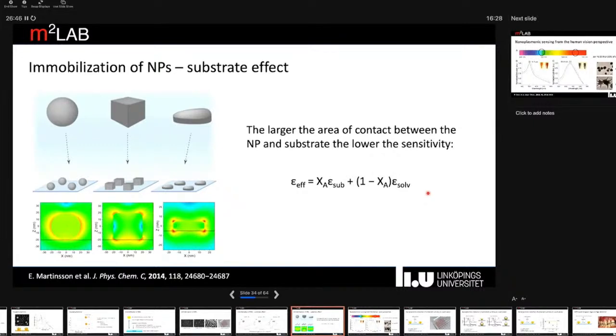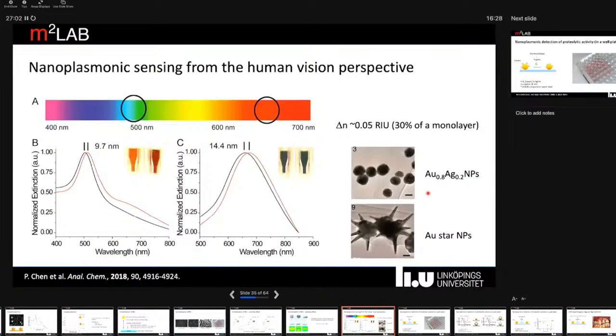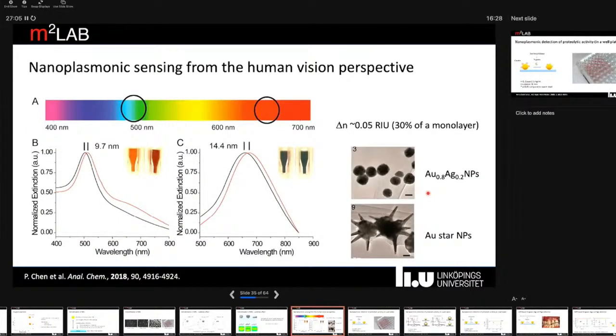And these differences are typically what we are talking about now with these particles. We typically rely on a spectrophotometer to monitor these changes in refractive index, but we can also, with some tricks, make them visible by naked eye. And that requires that we take the physiology of human vision into account. We can boost sensitivity by redshifting the plasmon band to have particles that produce a large shift in the plasmon band as a result of fairly small refractive index changes.